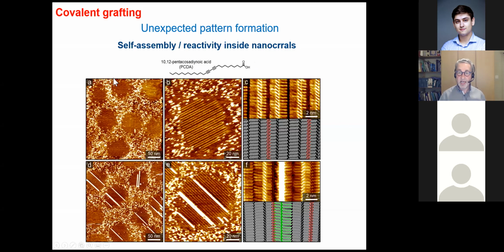Having formed these corrals, as we call them, you can then start to fill them with molecules. And how do we fill them with molecules? Easy. We expose this modified surface to a liquid with a molecule of interest. And this molecule self-assembles in rows inside these corrals. Actually, we create nano containers where we can investigate the self-assembled molecular network formation of molecules. So these are all individual and independent containers. As this is a reactive molecule, by shining a light on it, we could transfer the molecular organization to a polymeric one. Such a bright line is a polymerization reaction that has happened on the surface.